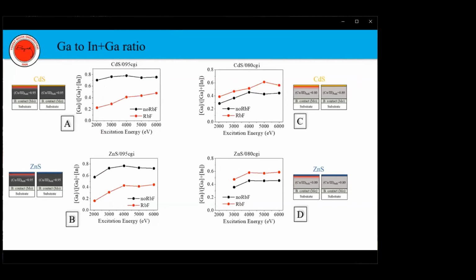In the following slide, I compare the gallium to indium plus gallium ratio of the samples. If we compare figures A and B, these are very similar. Both show a gallium enrichment on the surface before PDT, which is not influenced by the type of the top layer. Therefore, the high gallium concentration in the surface near region is probably related to the three-stage deposition of the absorber. After PDT, the relative gallium concentration with respect to indium strongly decreases in both cases. This effect can be explained by the formation of gallium fluoride secondary phases due to RbF PDT and removal of them by the ammonium-containing chemical bath.